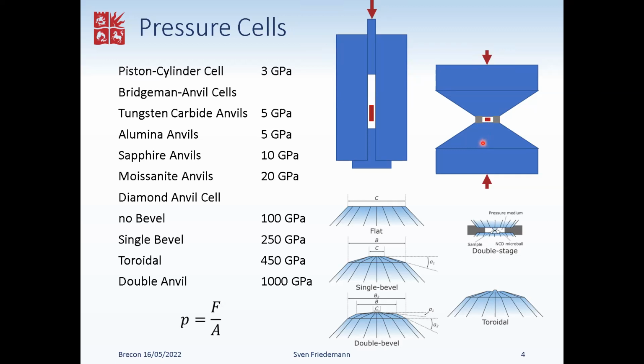The maximum pressure that is achievable with such diamond anvil type cells, or more general with anvil type pressure cells, depends both on the strength of the material as well as on the size of the culet. So strength of the material, cheaper but still strong materials like tungsten carbide give you 5 GPa. Alumina, sintered alumina cells, again 5 GPa. Sapphire, you can practically go to about 10 GPa. Moissanite, which is the gemstone name of silicon carbide, single crystalline silicon carbide, can get you practically up to 20 GPa. And beyond that, only diamond is left, because diamond being the hardest material and hence giving us the highest pressures.